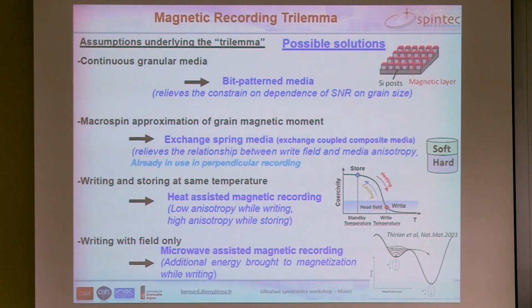Now we can also assist the writing in 2 different ways. We can assist the writing of the information, the switching of the magnetization, by a temporary heating of the media. And this is what I'm going to explain in the following of the talk. The idea is to use a high anisotropy material like iron platinum, which has very high anisotropy at room temperature. Then during write, we heat the media with a laser spot, which reduces the anisotropy of the media. Then we can, with a weak field, switch the magnetization. And after switching, we let the media cool down, and the large anisotropy is restored.